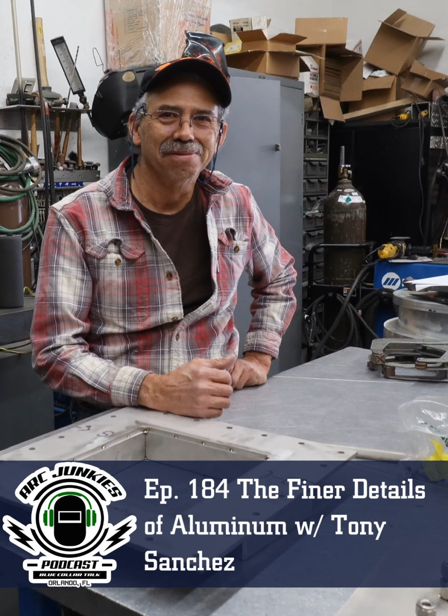You know what face-centered cubic material is, correct? I don't. That's a new one on me. That's the crystalline structure, your stainlesses and your aluminums. They have very little carbon in them, so there is more theory on the cooling process of that material than there is in the heating process. Totally 100% opposite of carbon steel, correct? Correct. You always want to preheat carbon steel, especially if you get an elevated carbon content. Well, the same thing with aluminum, you want to warm it up, but pull it back cold as fast as you can.